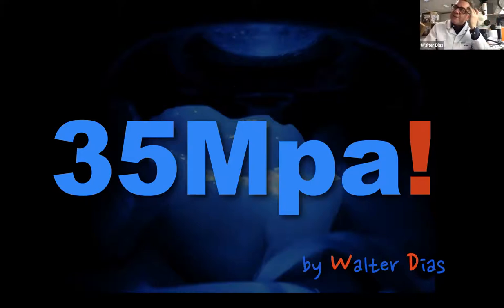As I said, the adhesion to dentin is not 100% stable. You will have some degradation with time. The bond strength to dentin is going to decrease. But the question is, if we achieve the highest bond strength, is this still going to be functional after 10 years? And the answer is yes.